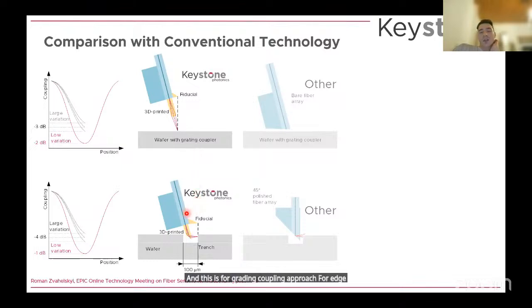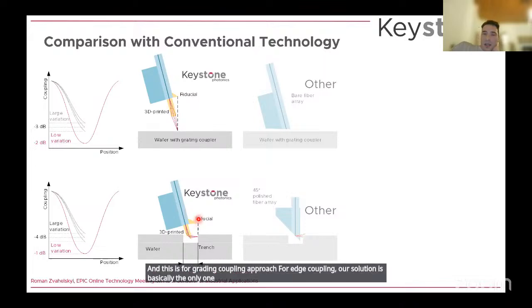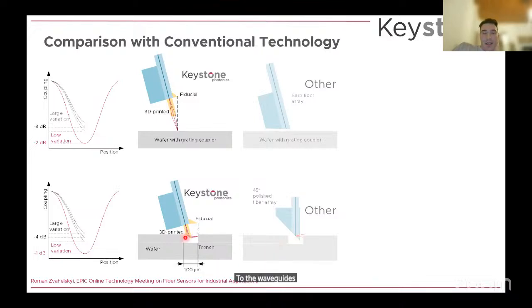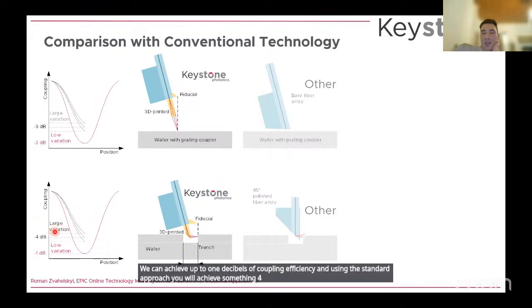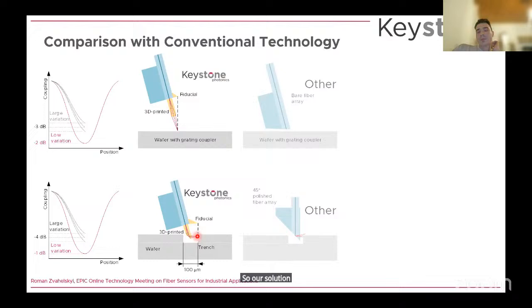For edge coupling, our solution is basically the only one, because the only possible alternative to edge coupling is using a 45-degree polished fiber array. And here you need to move the fiber array as close as possible to your edge, to the waveguide. Using our approach, we can achieve up to 1 decibel of coupling loss, and using the standard approach, you will achieve something like 4 dB, with very large variation. And if you want to improve coupling efficiency using the standard approach, you basically crash the fiber array into the trench. So our solution provides a very efficient method of optical coupling using trenches and edge coupling.